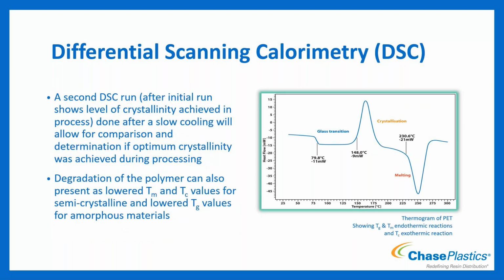The other thing that it can show us, which is helpful if we're getting really deep into figuring out part failure analysis, is for our semi-crystalline materials, because we can run it a second time, we can compare the level of crystallinity achieved during process. Your second run, after there's a slow cooling process, will allow us to know how much is the optimum crystallinity and if we are achieving that. So if you're running a semi-crystalline material, a PET, a PBT, a nylon, and you're processing it with a mold that's too cold, we're not allowing it to crystallize to the full optimal amount. And so we basically rush through its cooling cycle. We don't allow it to crystallize adequately.